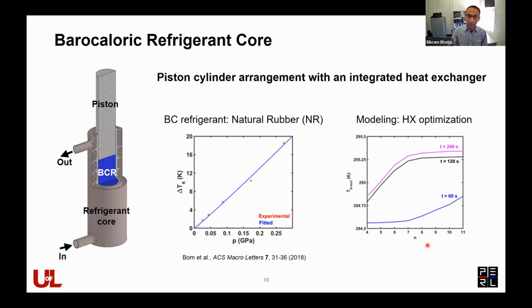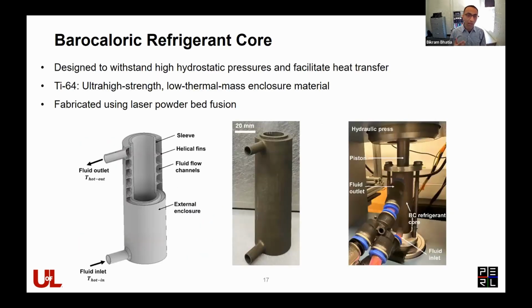And so based on these results, we said, okay, around 8 coils, 8 passes is good enough because we don't want to have a lot of thermal mass of the heat transfer media around the barocaloric core as well, because that slows down the performance and reduces the heating power. So we settled on around 8 passes for the helical heat exchanger. And then we went ahead and built it.